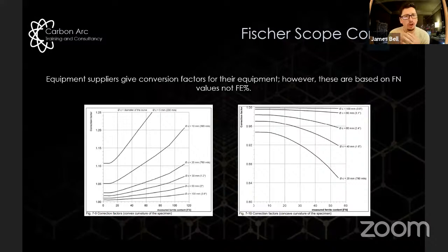Now, there was a lot of discussion at the time around how do we convert a ferrite percentage number to a ferrite number, and it became a big bone of contention, not just internally within the company, but also between us and our client. Because how do you decide what a ferrite number is if you don't fully understand, a martensitic structure in your material is going to throw that out, what the phase balance is like, all that type of stuff. So very quickly, these conversion graphs became really a non-starter for us, and we couldn't apply that.